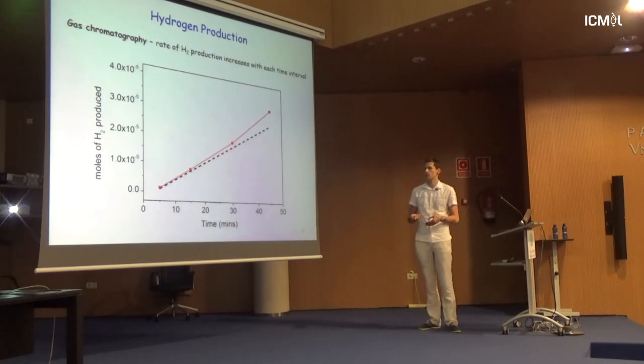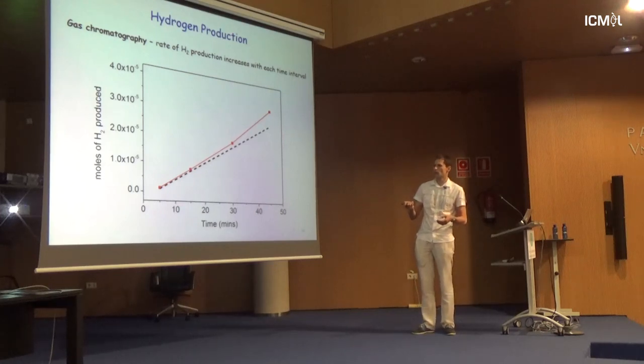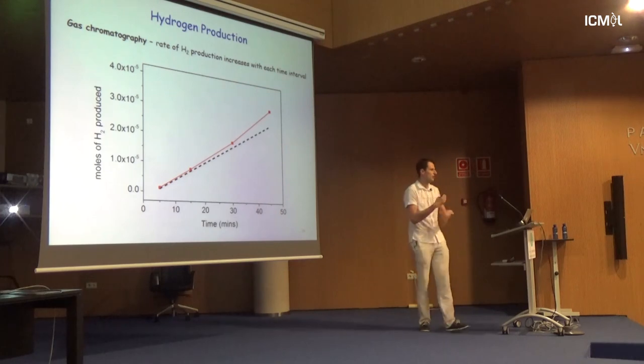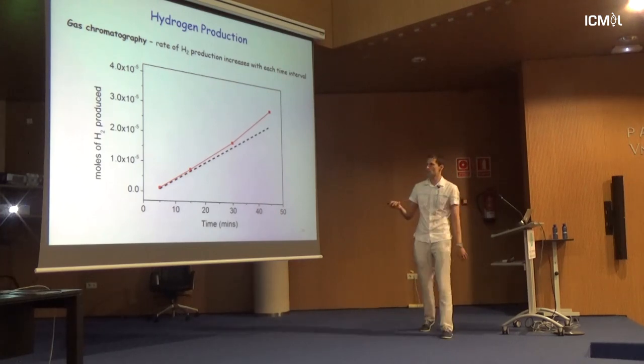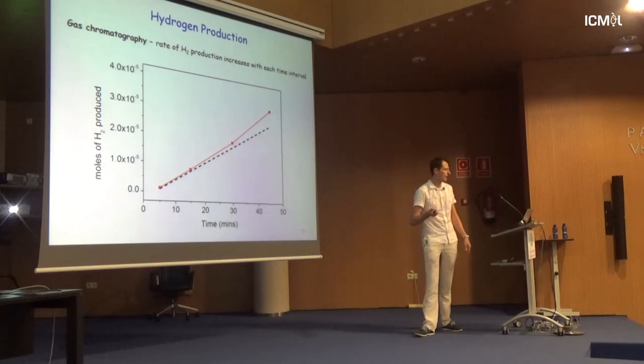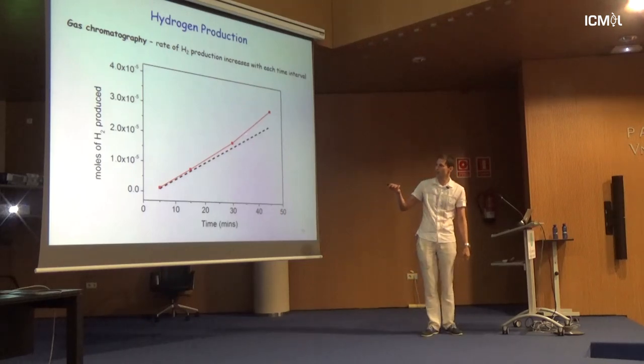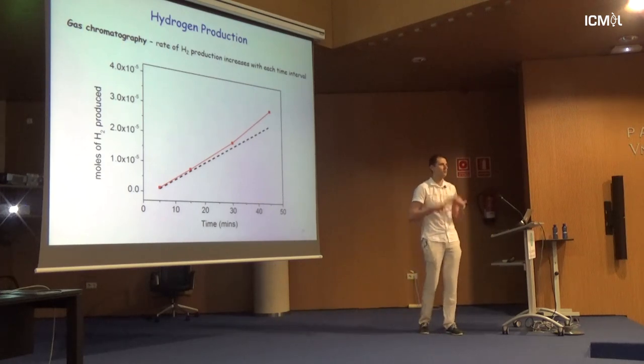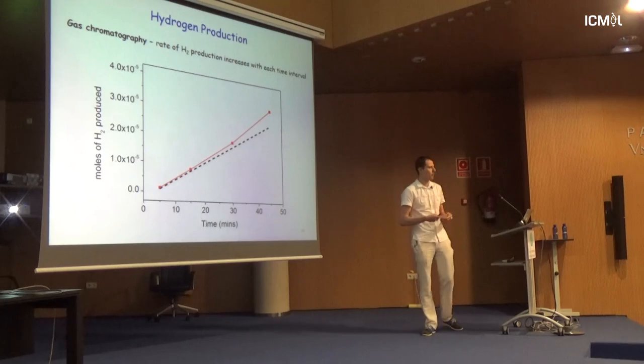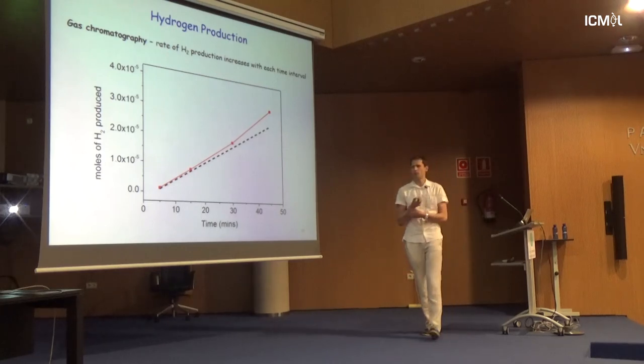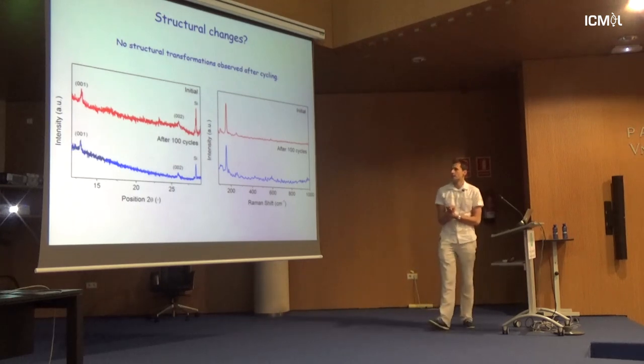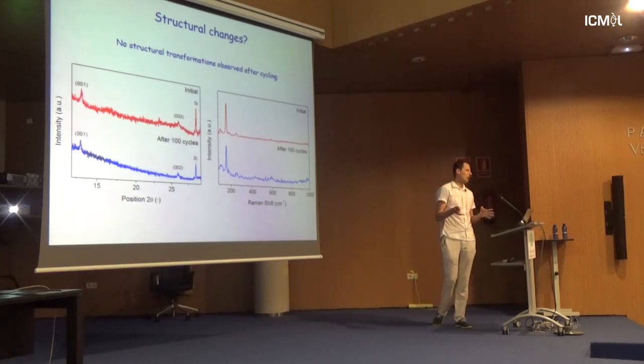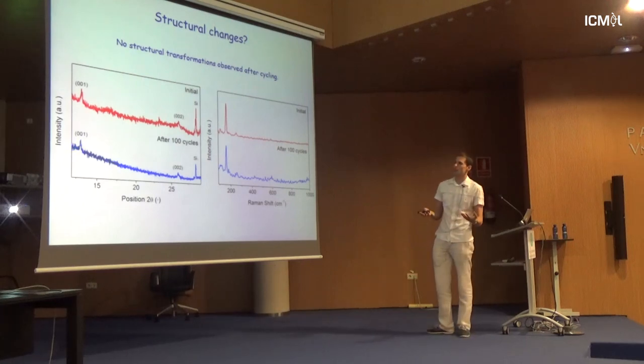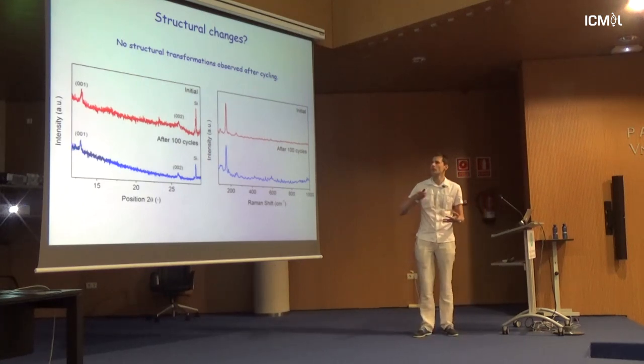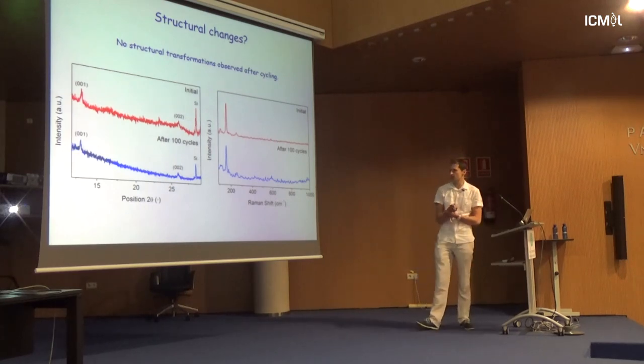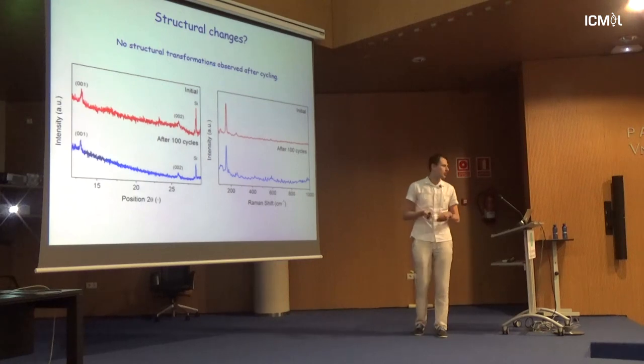And what we also did, you would expect your hydrogen evolution to go down, so materials typically will be steady, or once you start producing more hydrogen, your gas cell will leak a little bit. But what's happening is quite an interesting thing. You're producing more hydrogen. As you cycle it, you're producing more and more hydrogen. So this material is getting self-optimized. Okay? And so we obviously thought, oh, there must be some structural transformation. And so we did again in situ XRD and in situ Raman, and there's literally nothing.